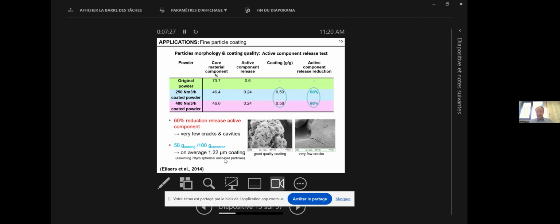And at lower airflow rate, you dry a little bit slower and you have somewhat more agglomeration. So here you have really minimum agglomeration. We had a very fine layer deposited. You see that here. The particles were on average, I think, 70 micron, and we deposited a layer of 1.2 micron on those particles, with very few cracks, to be honest, resulting in a 60% reduction of the release rate of an active component, which was fat, if I remember well.